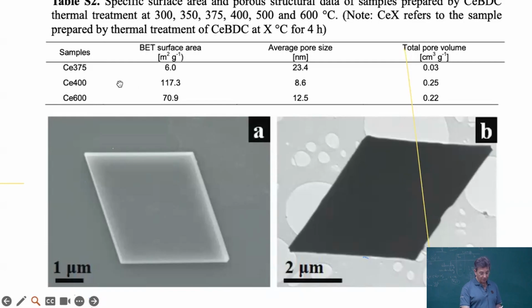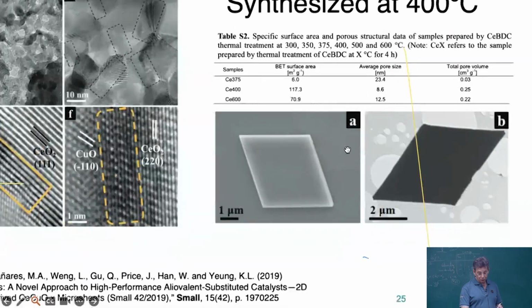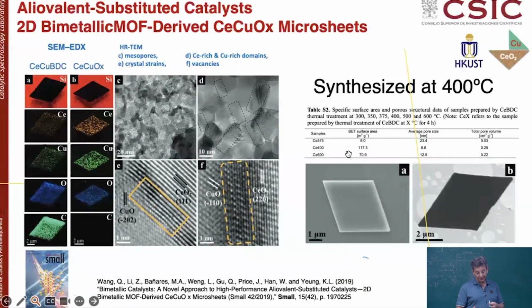So basically, our combustion was made at 400, where you have a maximum area, and also you minimize sintering phenomena that will result at higher temperature in better crystalline definition, fewer defects and less reactivity, or incomplete combustion like it happens at the lower temperatures.